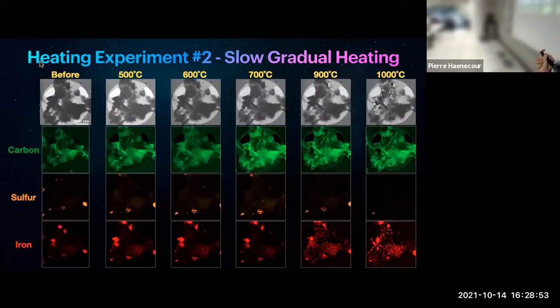In terms of composition, we see the exact same trend that we saw before. The signal becomes stronger and stronger in carbon, especially at temperatures above 600 degrees. Same for sulfides: not much happened until 700 degrees, and then above 700 degrees you lose most of the sulfur. Most of the sulfur is volatilized in the vacuum, and the iron is relocated into those nanoparticles. So the iron nanoparticles are forming from both the silicates that are present and a lot of those iron sulfides.